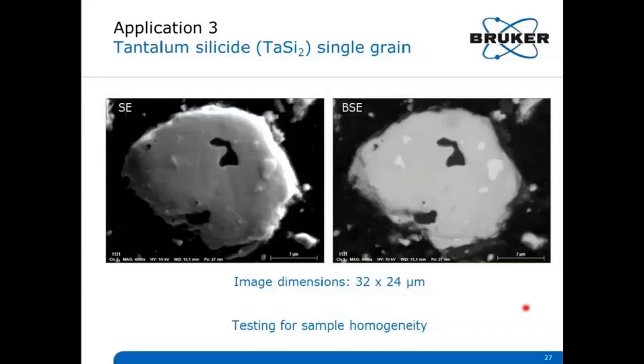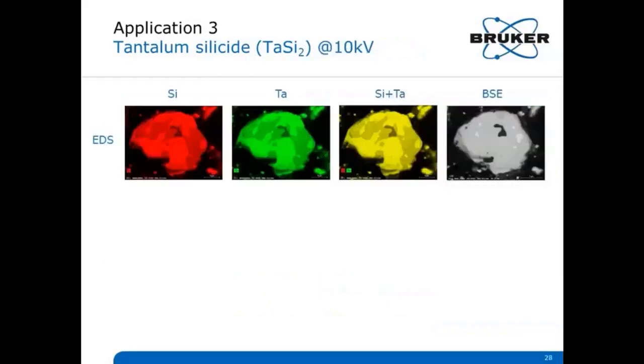We clearly see darker areas and bright inclusions here within the single grain, the single particle. This is clearly indicated in the BSE image here, darker inclusions and brighter inclusions. We acquired EDS and WDS maps on the present particle labeled as tantalum silicide. And this first row of maps shows the EDS maps for silicon, tantalum, and a combination of both elements compared with the BSE image.